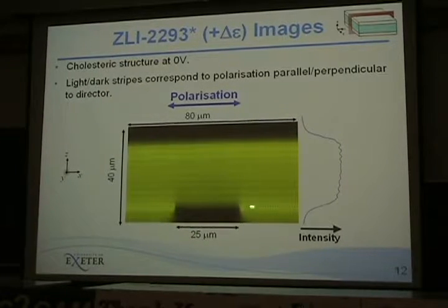At the top and the bottom we've actually got glass, and the dotted line is showing us where our silver electrodes are. You're going to have to use your imagination and pretend that the one bit is black, because one of the problems of focusing using the confocal microscope into a point that's actually below an optically thick silver mirror is the light gets reflected back up into the system, so you end up with this sort of false image, which actually comes from a point equidistant above the electrode. And that's a particularly interesting optical technique, but will be a whole different presentation, so we're going to ignore anything